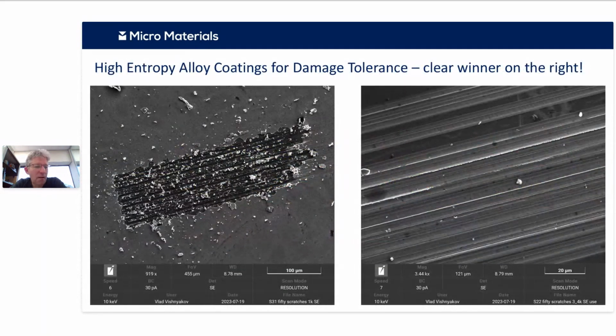So here's another example, in this case for a nuclear application, a collaboration with the University of Huddersfield. And here what we're seeing essentially is two different high entropy alloy coatings that are very mechanically similar, and they're being tested here under the same conditions. But what you can see is that the one on the left is much more brittle than the one on the right. So the one on the right is clearly a much more abrasively resistant coating.